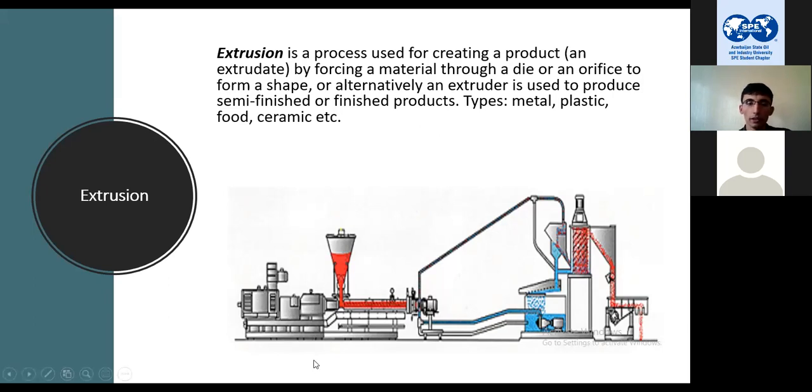In the extrusion area, everything is mixed and melted. The temperature is around 200 to 230 degrees Celsius there. It's all mixed, melted, transferred, and then cut. Then we have what we call PCW, which stands for pellet cutting water. The water solidifies the product and also transfers the cut pellets to the separator, dryer, and then the classifier, and then finally we have